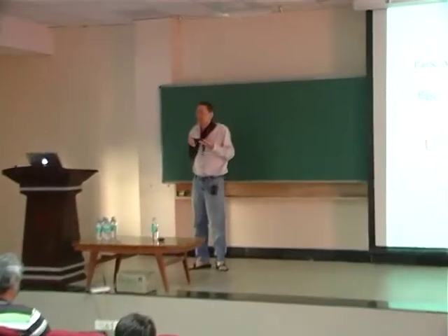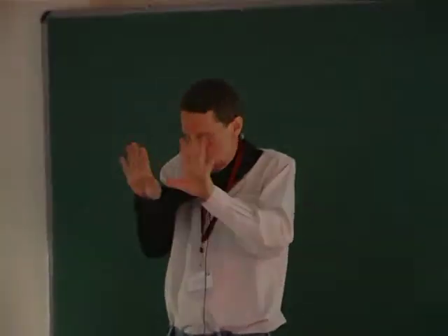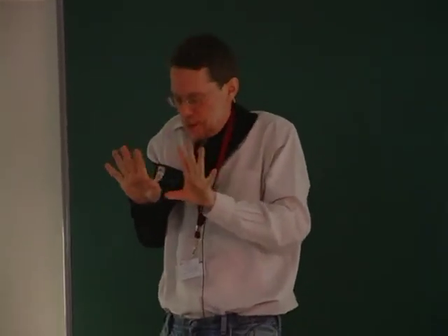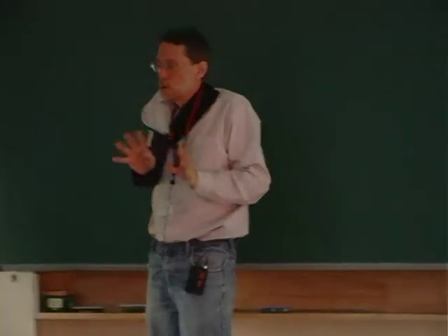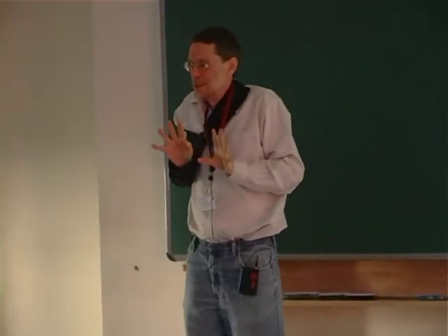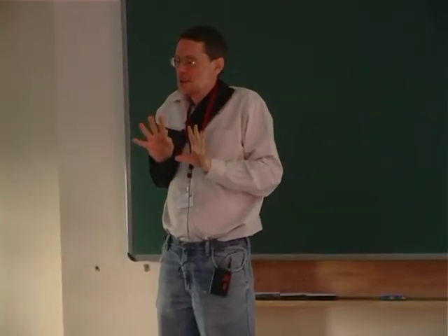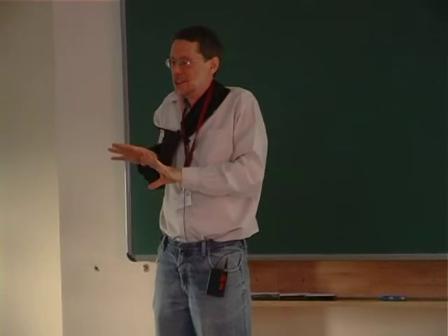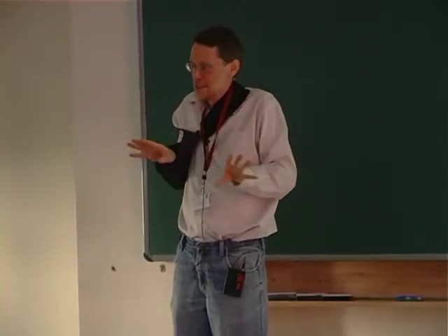There's a substantial U, and again, the question is how much of that does DFT get right? This is from constrained RPA. But I would agree that there's a large U on the oxygen. Furthermore, in these kinds of theories, even in the nickelates, which have an enormous amount of covalency, relatively speaking, the hole density on the oxygen is very small. You transfer approximately 1 electron from the oxygen to the d level. The nickel is d8, not d7.